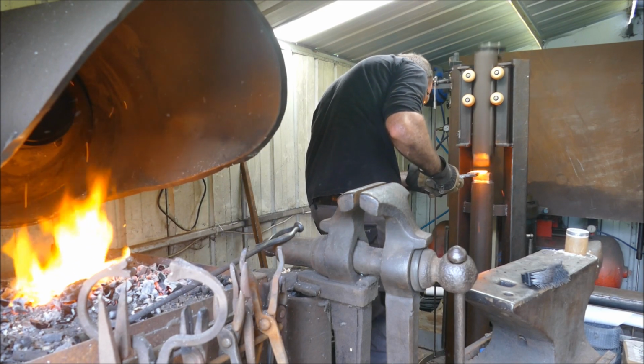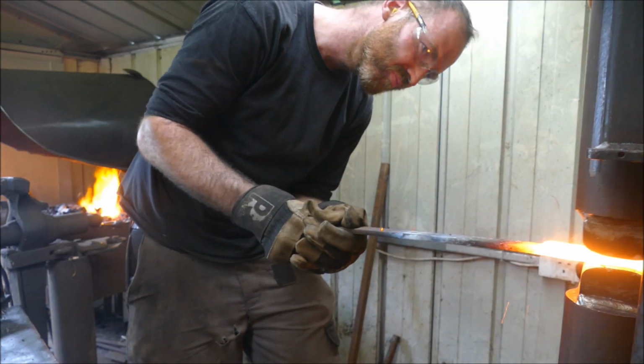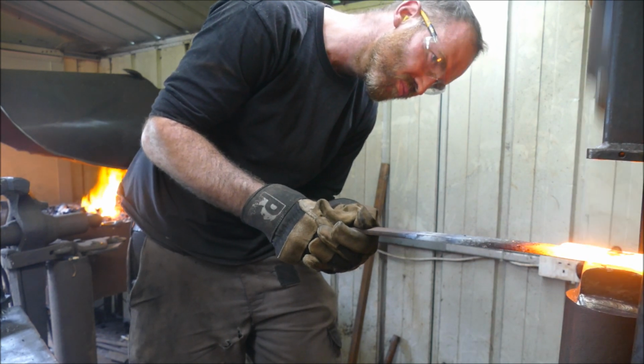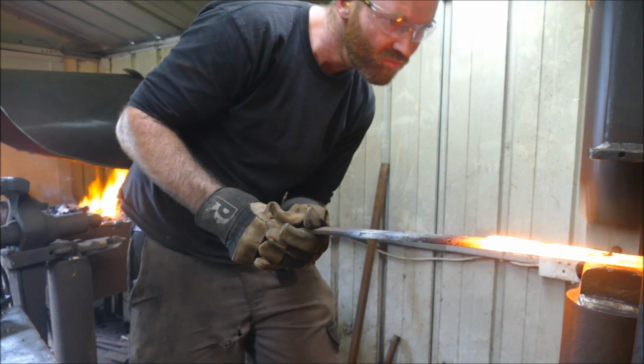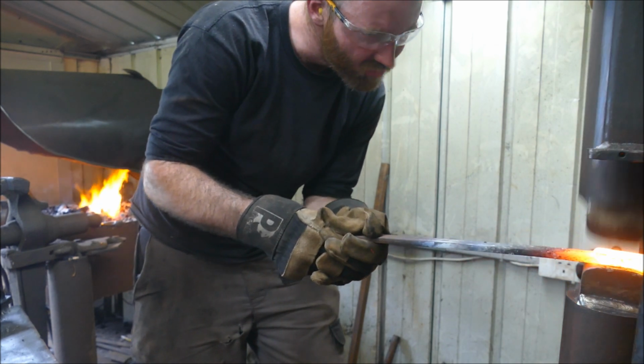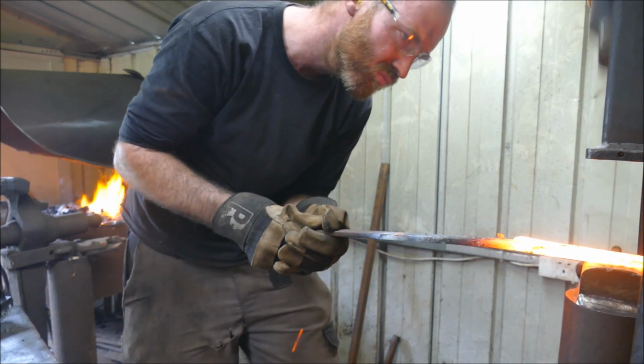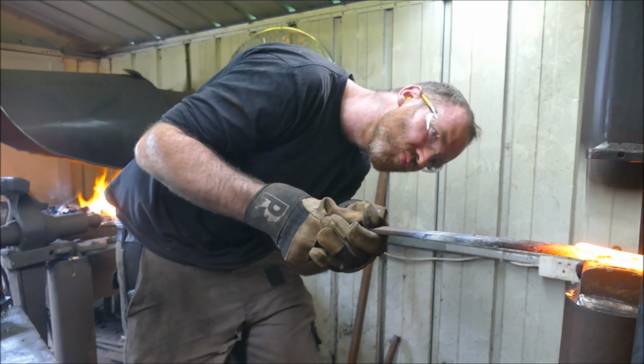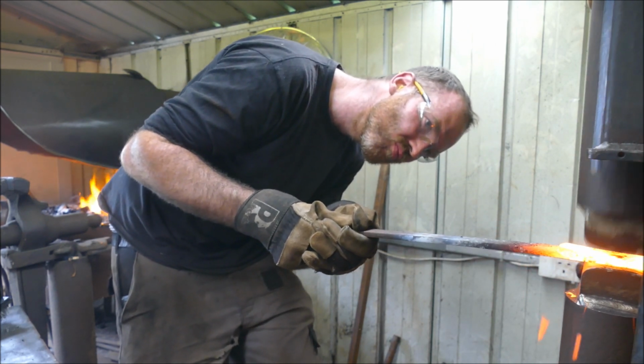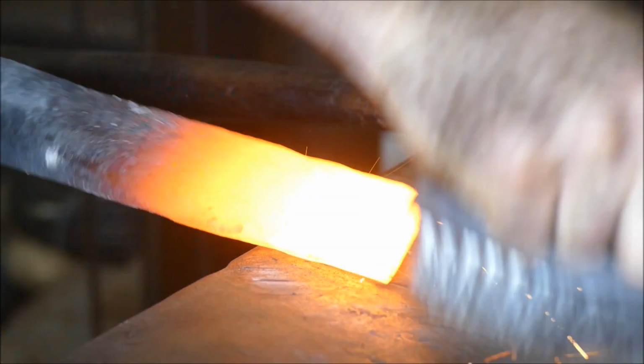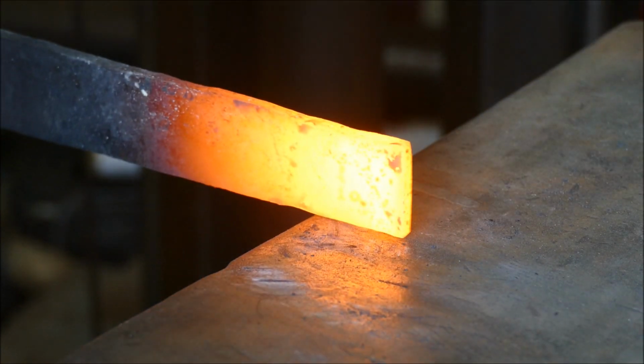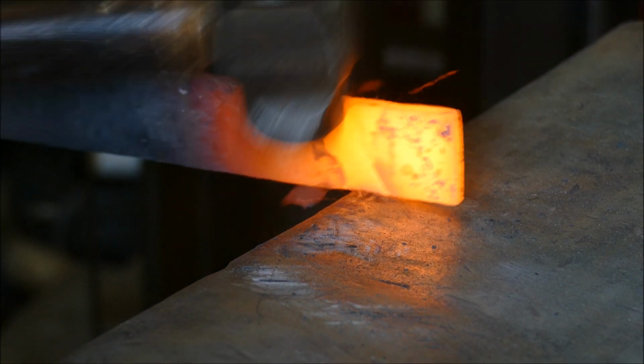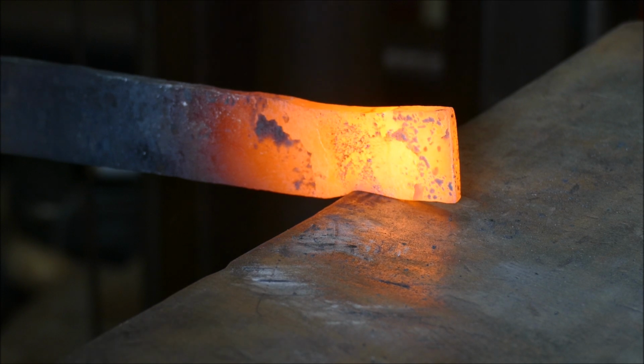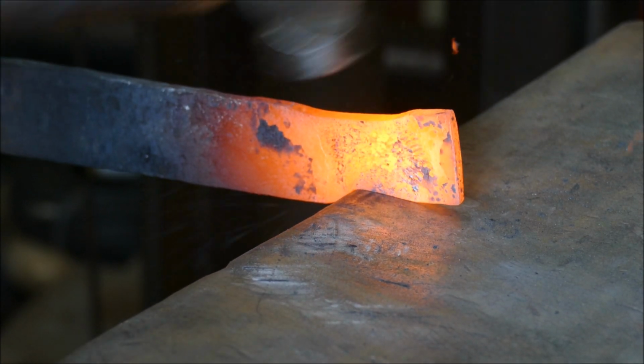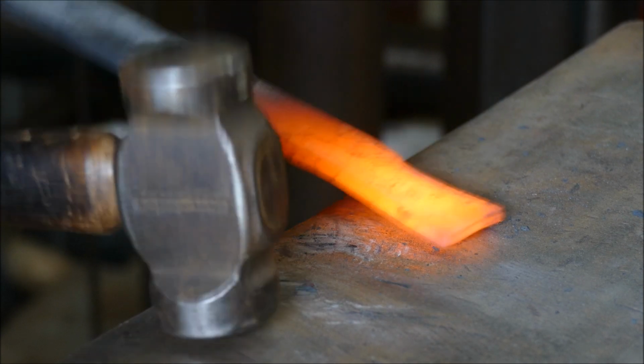Coming back to the idea of ironclad blade forging, there is another benefit which comes into the making part itself. Now you've been watching me use a flux called borax, which is stopping the steel from oxidization. Without flux, the high carbon steel is likely to burn away. But the other property of a low carbon steel or pure iron is that the melting temperature is far higher. On the other end of the spectrum you have cast iron, which has incredibly high carbon content for the very reason that it has a lower melting point and therefore is easier to cast.